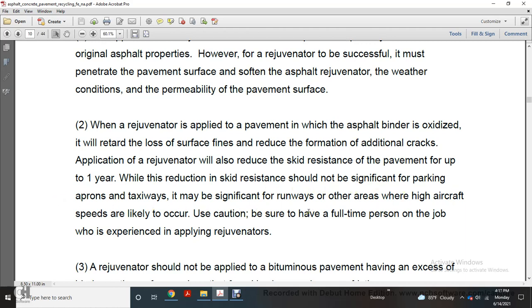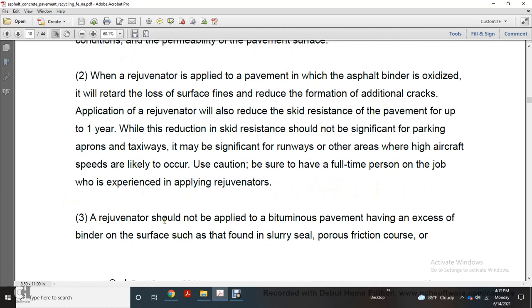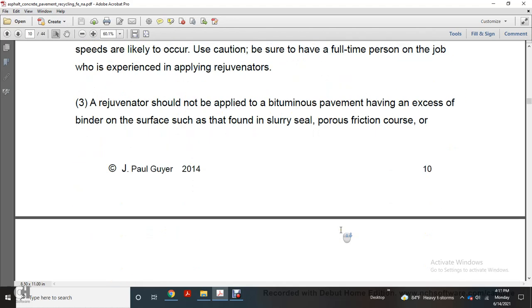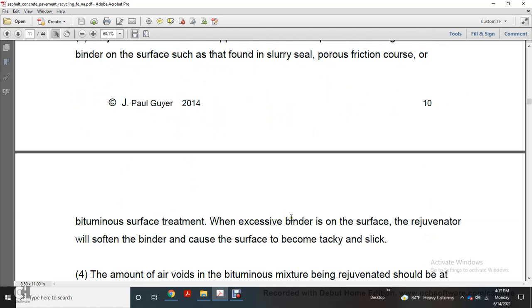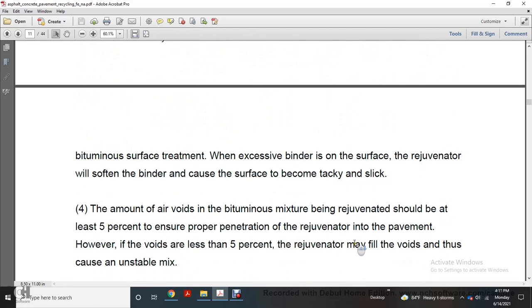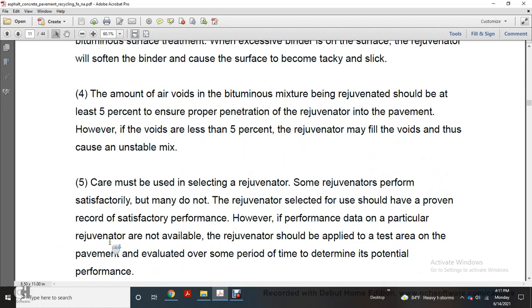Caution should be taken to make sure a full-time person experienced in applying rejuvenator is on the job. 3. A rejuvenator should not be applied to bituminous pavement having excess binder on the surface, such as is found in slurry seals, porous friction course, or bituminous surface treatment, in which excessive binder is on the surface. The rejuvenator will cause the soft binder on the surface to become tacky and slick. 4. The amount of air voids of the bituminous pavement mixture being rejuvenated should be at least 5% to ensure proper penetration of the rejuvenator into the pavement. However, if the voids are less than 5%, the rejuvenator may fill the voids and thus create an unstable mix.